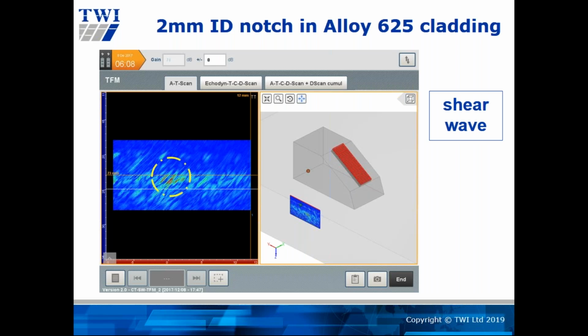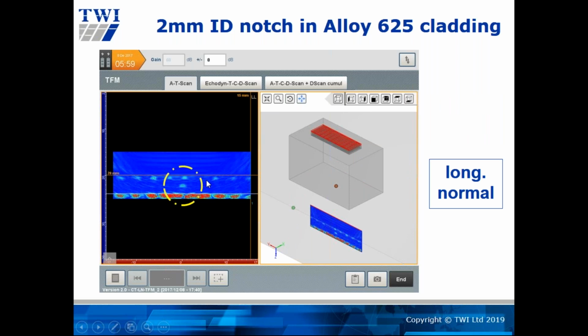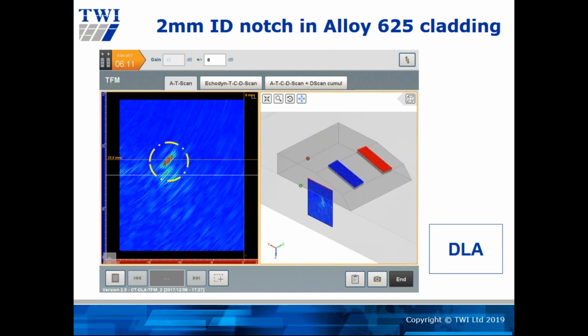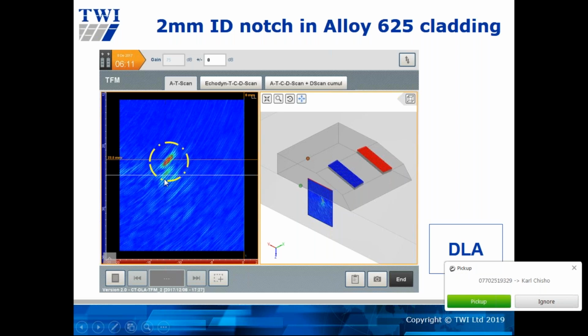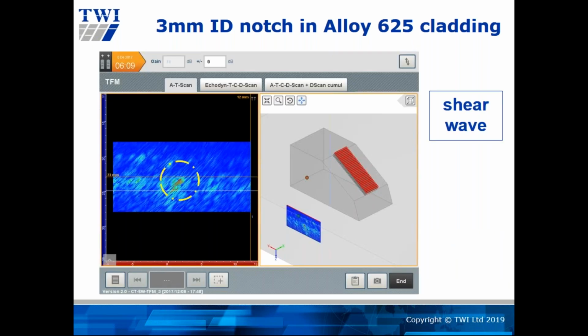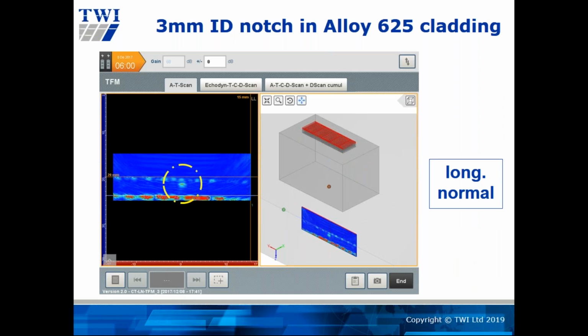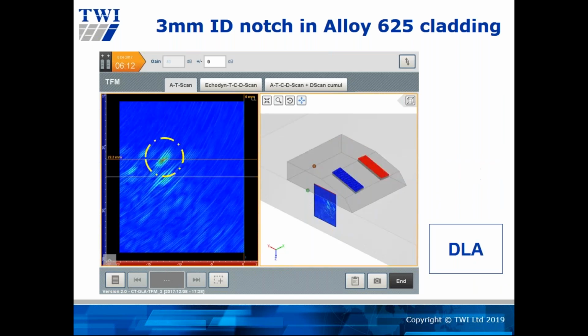Similarly, when we look at the 2 millimeter notch in the cladding, you see a lot of noise in the shear wave channel, and of course you can't really resolve the flaw itself. But once you move to the longitudinal wave mode, you can now see the signal from the flaw, which is where I'm circling with my mouse. And when you look at it with the DLA technique, you can see quite clearly the two facets of that flaw, allowing you to establish its extent. But noticeably, the noise in the image is much reduced. And again, similarly, with 3 millimeters, even though it's a 3 millimeter flaw, it's very difficult to resolve from the shear channel, but you can in the longitudinal normal channel and the DLA channel.